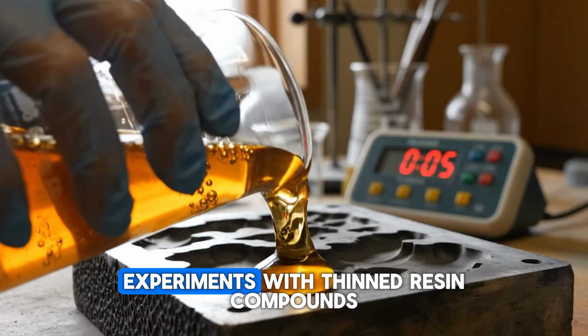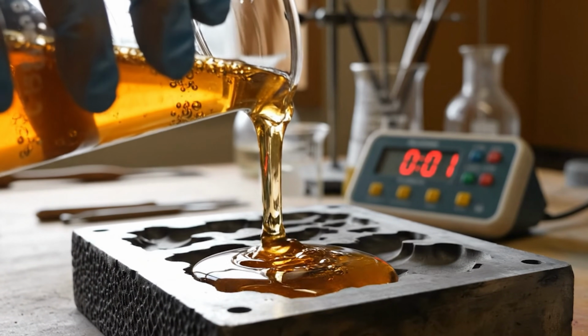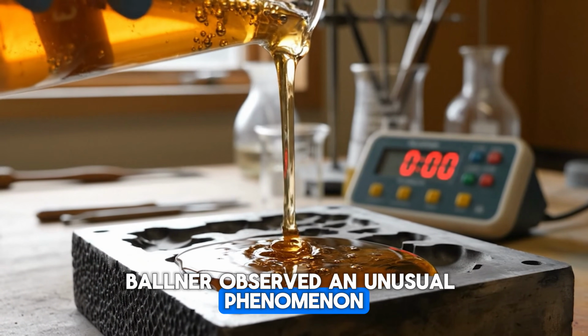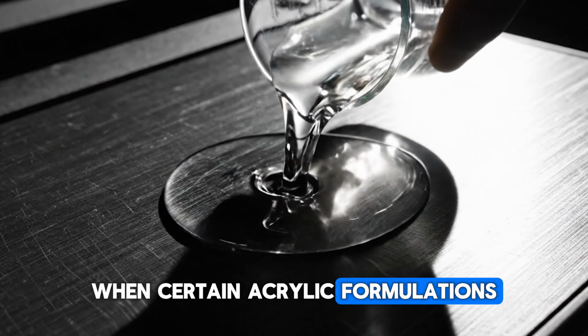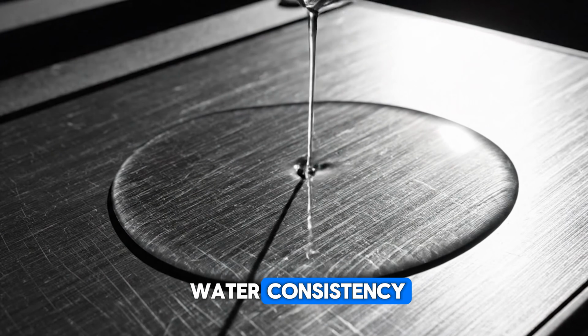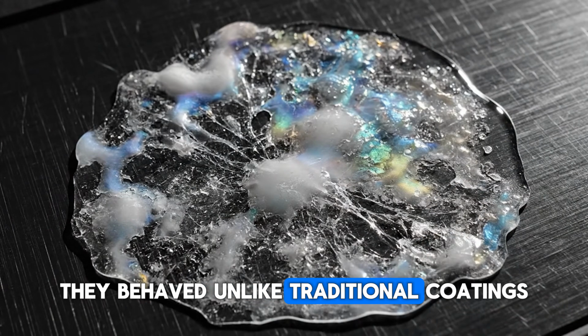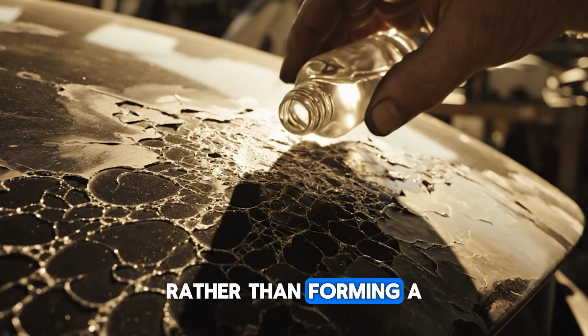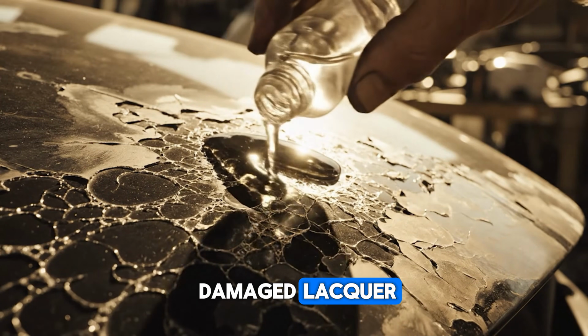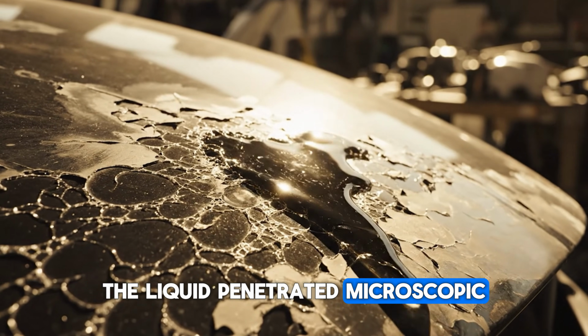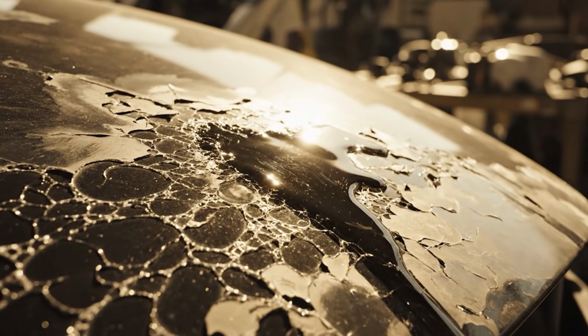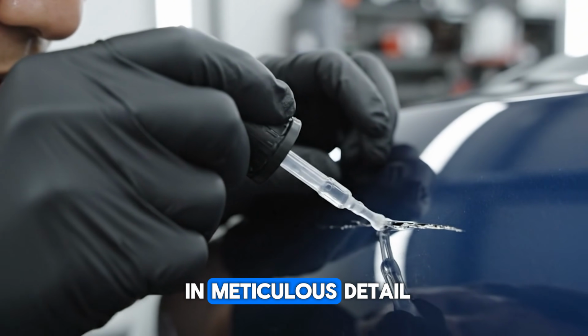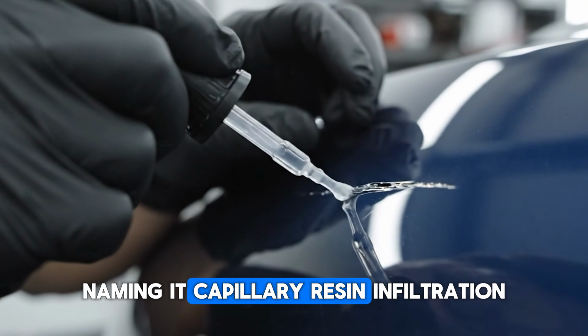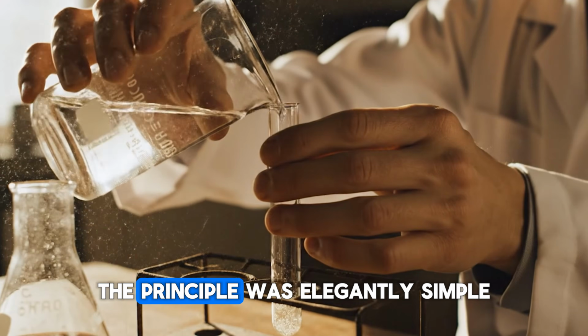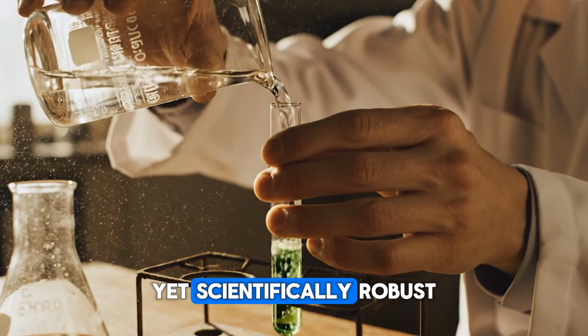During a series of experiments with thinned resin compounds, Ballner observed an unusual phenomenon. When certain acrylic formulations were diluted to near water consistency, they behaved unlike traditional coatings. Rather than forming a layer on top of damaged lacquer, the liquid penetrated microscopic fractures and hardened from within. He documented the process in meticulous detail, naming it capillary resin infiltration. The principle was elegantly simple yet scientifically robust.